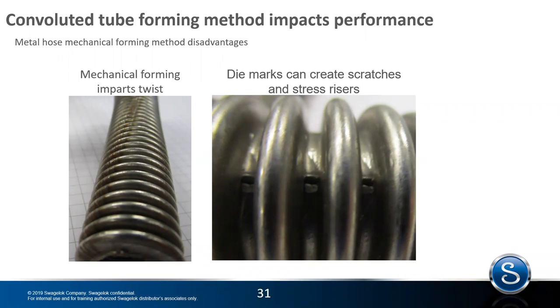A mechanically formed hose with rollers is basically twisting the hose before it's even applied to an application. So the hose already is starting behind the eight ball, if you will. It's already losing life because it's twisted. And what happens as the hose goes through multiple bends is the root of these corrugations cracks, similar to a paper clip. And that's what you see on the right side. The actual roots break and you get a leaking hose.